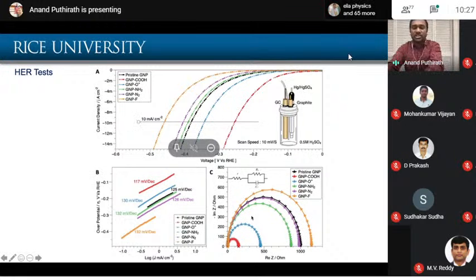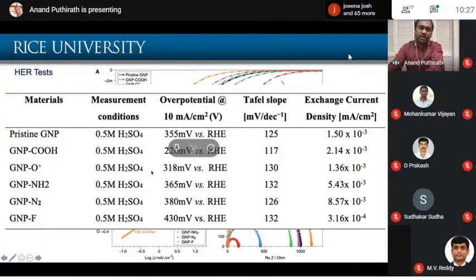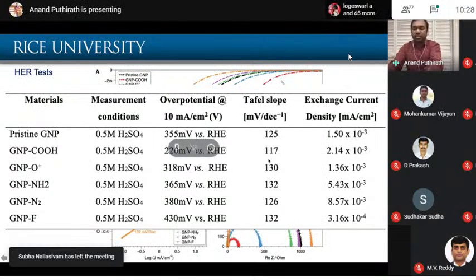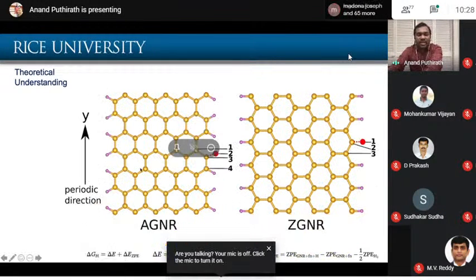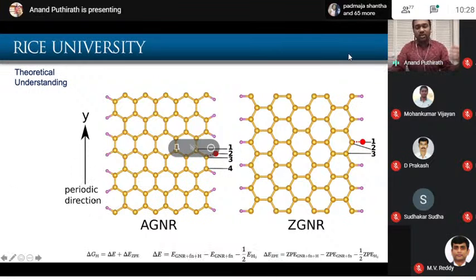And if you see the charge transfer resistance and a few other things, here also there is a trend. For COOH it's least, and for fluorine it is high. And these are some typical parameters people look into when you systematically characterize a catalytic material. You want to know the overpotential, at what voltage splitting happens, how fast it will happen, and what is the exchange current. Those kinds of things are always there. And we are trying to understand what happened to the system and why this trend, and how you can really explain this trend. And what we want to see is the free energy of adsorption and desorption.